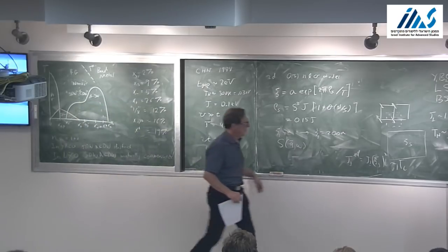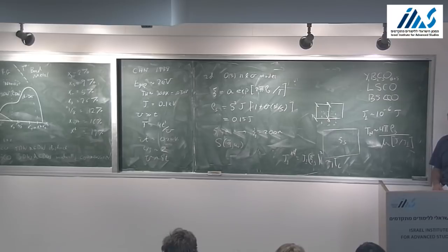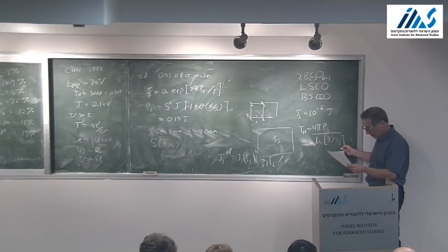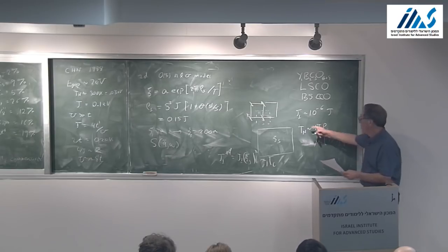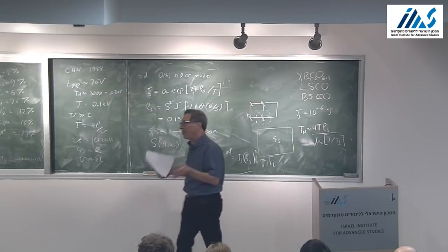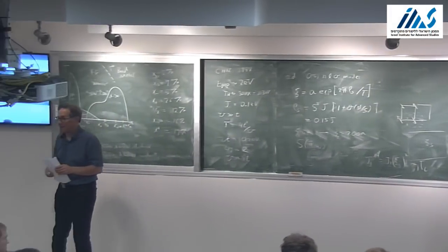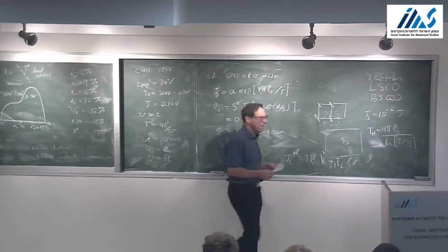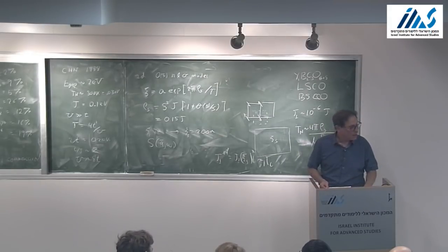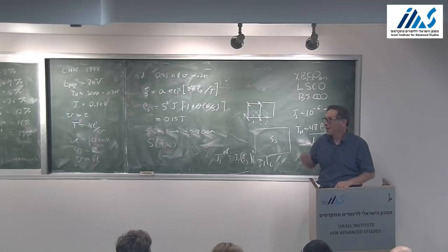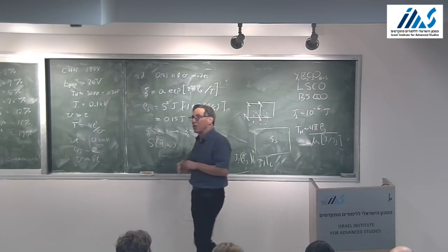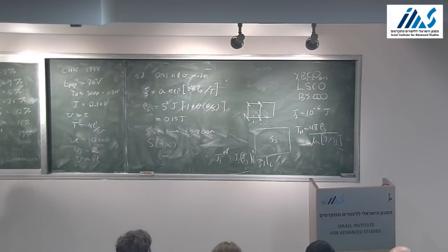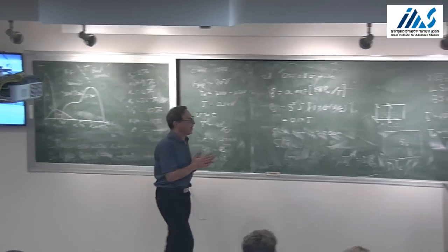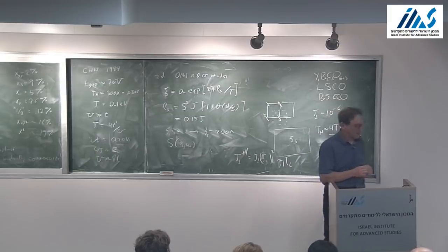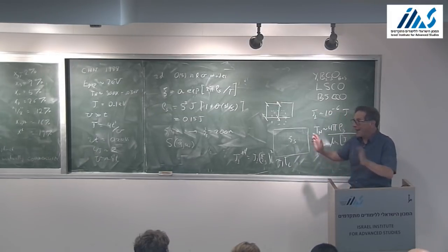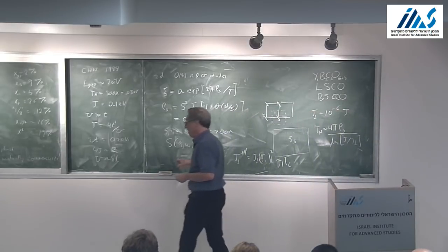And so even though J over J perpendicular is 10 to the sixth, the log of 10 to the sixth is 14. And so the Néel temperature comes out to be something like a third of J. So even though this thing's enormously anisotropic and two-dimensional systems can't order, even this enormously weak three-dimensional coupling produces a substantial Néel temperature. All right, so that's the undoped problem. That's, I think, really a solved problem.